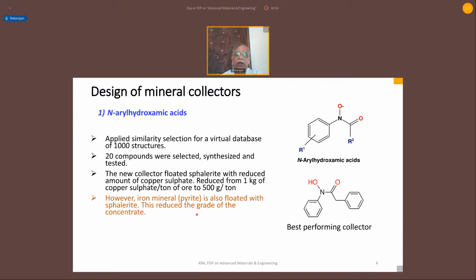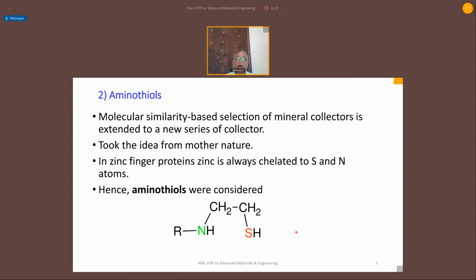When sphalerite concentrate is contaminated with pyrite, the value of the concentrate goes down, by $1 per ton of ore. Therefore, pyrite coming up in the concentrate is a detrimental factor. That means, though we found a scientific method for synthesis of collectors, the collector we synthesized is not very selective for zinc. Therefore, we wanted to try the next series of collectors.